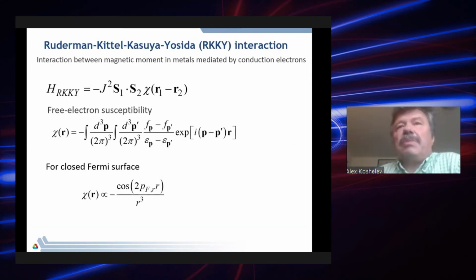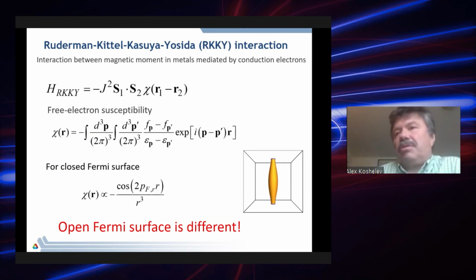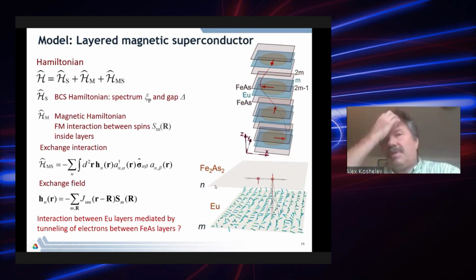I briefly remind what the Ruderman-Kittel-Kasuya-Yosida interaction is. This is the interaction between magnetic moments in metals mediated by conduction electrons. Basically, one moment modifies the spin density, which propagates over large distances, and the second moment feels this spin density. And this interaction is determined by the non-local free electron susceptibility, and it has a very famous, celebrated oscillating shape, which decays slowly and oscillates with a wave vector given by the Fermi momenta along the direction of propagation. However, in this case, the situation is totally different because we have an open Fermi surface and we don't actually have Fermi momenta in the direction we are interested in, along the c axis. The theory requires modification.